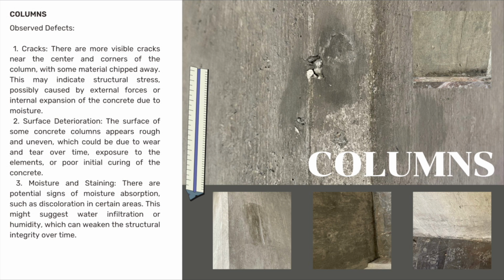Since the building is exposed to humidity and temperature changes, the contraction or expansion of materials can cause these microfissures. Now, moving on to the columns of the basement floor, some observed defects were cracks, surface deterioration, and moisture and staining on some columns in this floor. For cracks, there are some visible cracks near the center and corners of certain columns, with sometimes a bit of material chipped away. This may indicate structural stress, possibly caused by external forces or internal expansion of the concrete due to moisture.